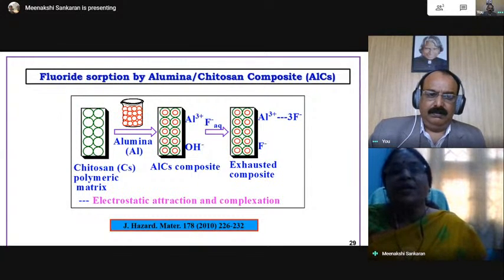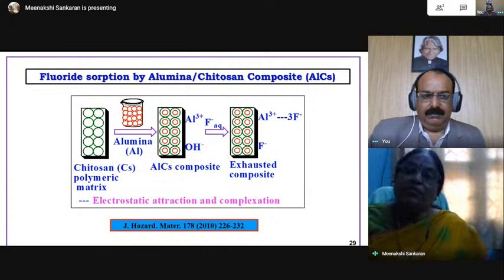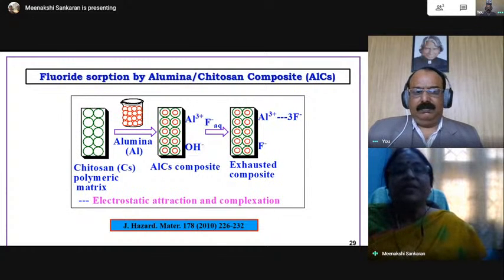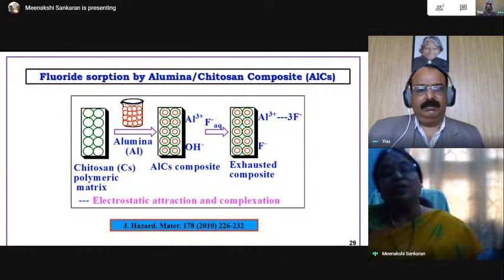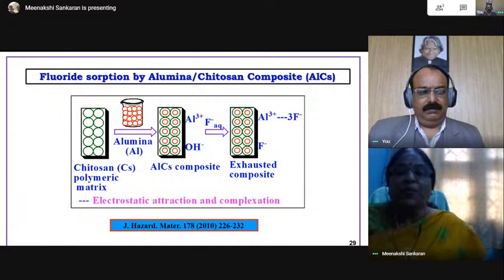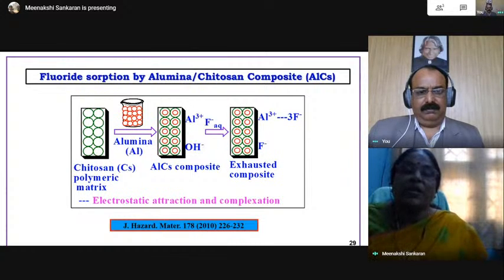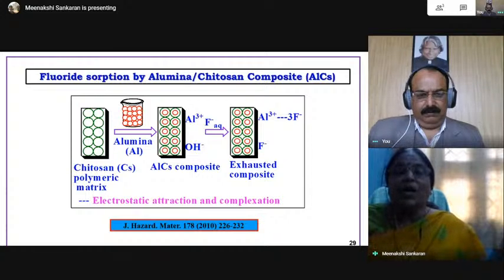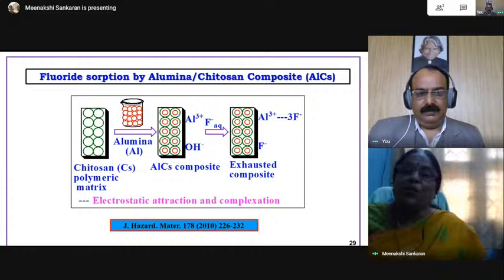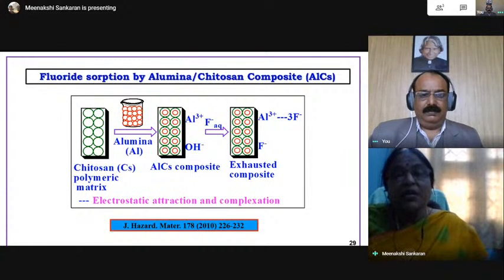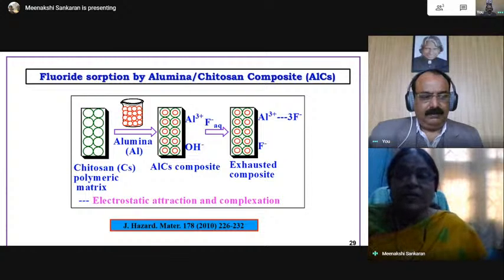So we have mixed alumina and chitosan. Both alumina and chitosan are capable of removing fluoride, and when we mix them, they are not very soft and not too rigid. They possess medium properties, enough mechanical strength and all. In alumina, we have aluminium Al3+ and OH minus groups. This aluminium attracts or removes fluoride by electrostatic interaction. The hydroxyl groups get exchanged for fluoride, as they are similar in charge. So hydroxyl groups are replaced by fluoride. By ion exchange as well as electrostatic interaction, this material removes fluoride.